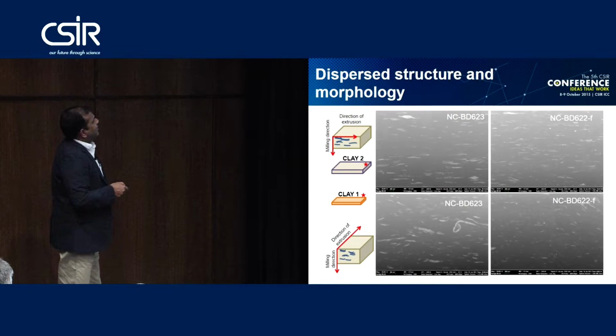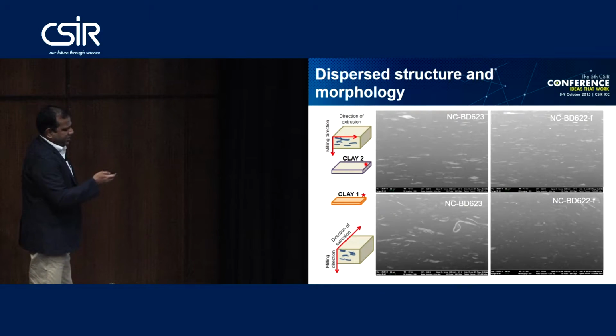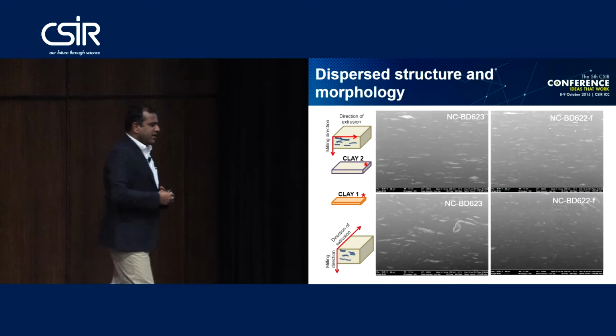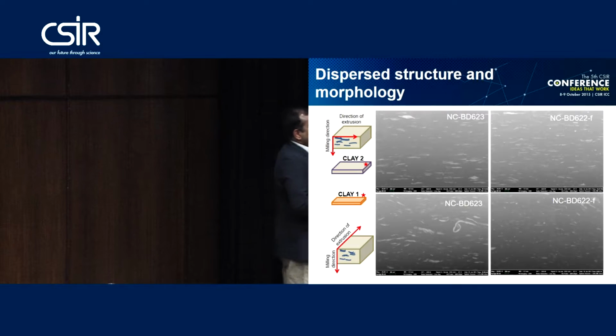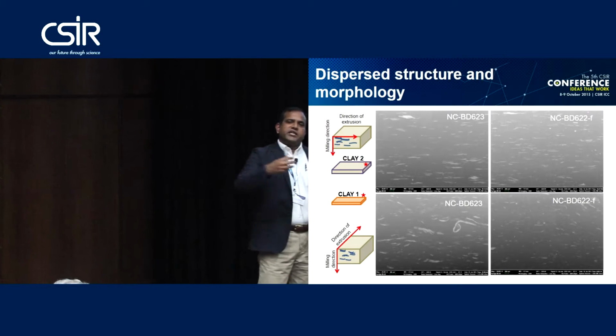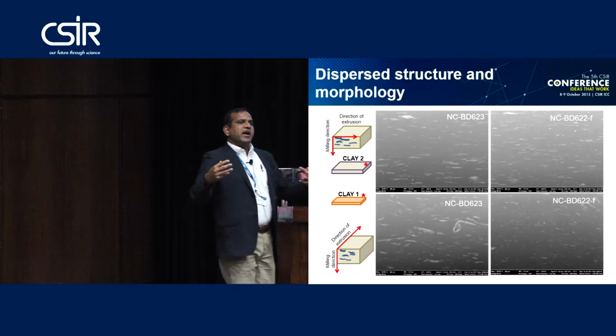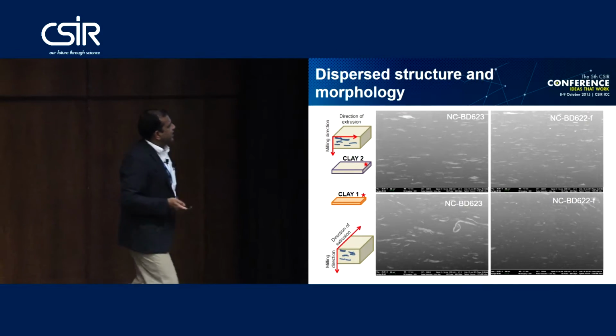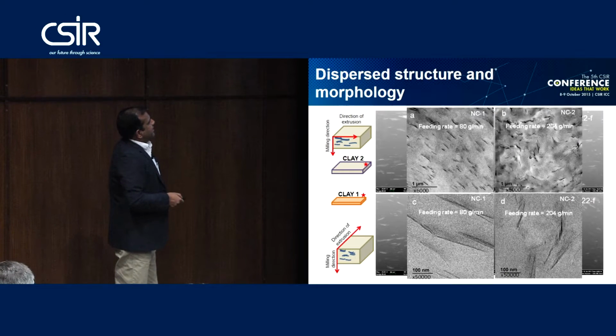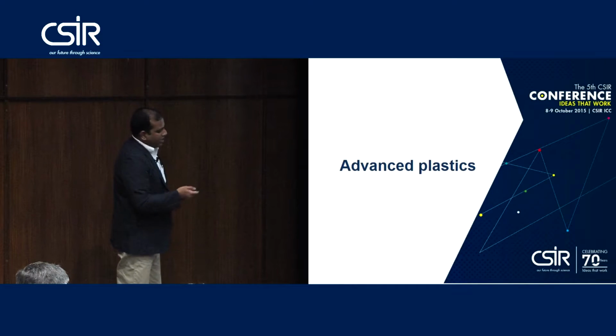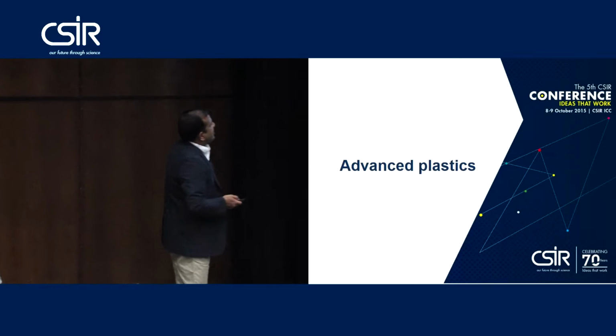And this is some of the dispersion; you can see the nanoclay platelets in the polypropylene matrix. One of the beauties of this is that you can control the dispersion by doing different kinds of surface chemistry. And sometimes you also need orientation of your nanoparticles inside the matrix to have better mechanical and barrier properties. You can see these are nanoclay platelets. The thickness is less than 1 nanometer and the length is a couple of hundred nanometers. So I'll show you some examples of advanced plastics.